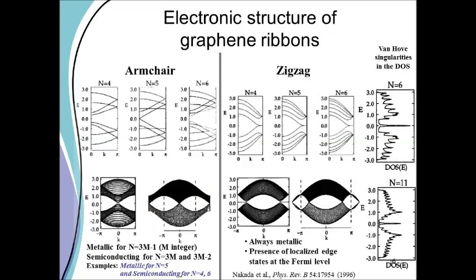This all started with an idea. Somebody came along and wanted to see the density of states of electrons in carbon. So we did some density of states calculations, and we came up with this really remarkable result: for these zigzag edges that I showed you, which look like a zigzag, you get this huge density of states right at the Fermi level. This is 0 energy, the Fermi level. And no matter how thick the ribbon is, any width, you always get that high density of states. So that's something that's going to be resonant. It's going to be a large, big enhancement factor from the physics. So we can go look for that.